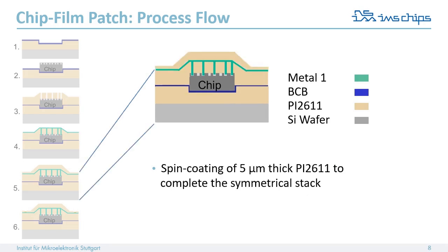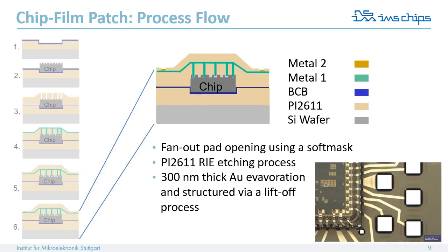Due to the fact that the 30 micrometer thick chip shows a bit more warpage compared to a bulky silicon chip, polyimide is spin coated in order to compensate this stress effect. In general, the ChipFilm Patch technology is well suited for embedding ultra-thin chips. However, it requires good knowledge of the material properties to compensate the thermal mismatch.